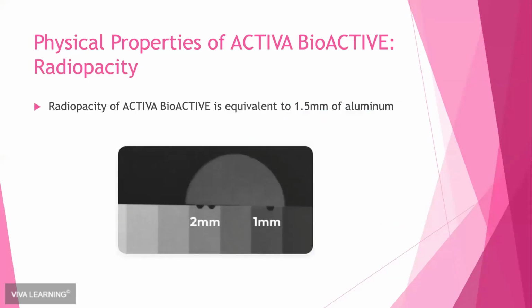And finally, radiopacity. This is something that as a clinical dentist is really important to me. I want to be able to see my fillings on a radiograph. I hate that feeling when you look at an x-ray, usually in the anterior region, and you think, is there a filling in that tooth? Is something missing? So when you look at this x-ray here, you can see that the radiopacity of the Activa bioactive material is equivalent to 1.5 millimeters of aluminum. So you will see this on your x-ray recalls when you're following up with your patients.